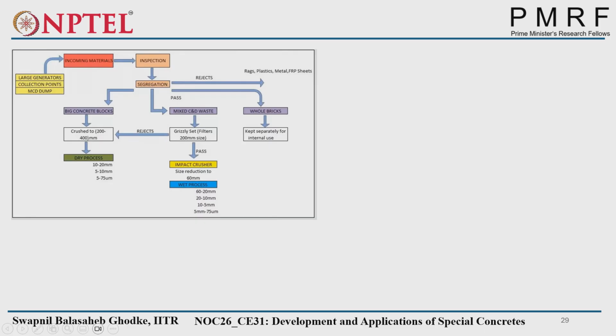Then the construction and demolition waste mix will come here. The whole bricks we can completely use for other construction, so they will be kept separately for internal use. The mixed C&D waste may be some broken aggregates, some broken mortar, some broken bricks, and some cementitious fines. For that purpose, filters will be available. Out of that, the material of about 200 that is rejected will come here.